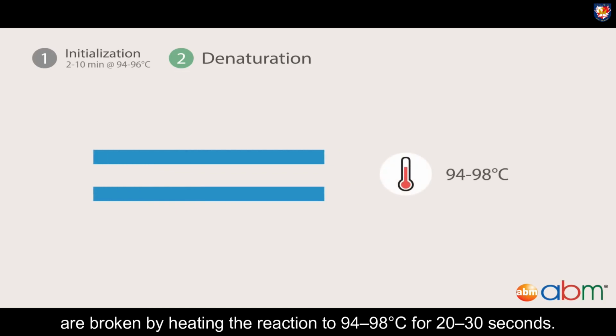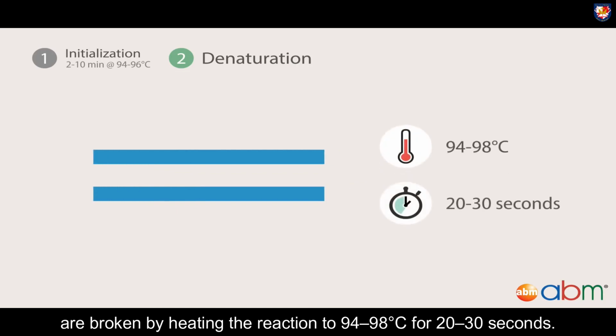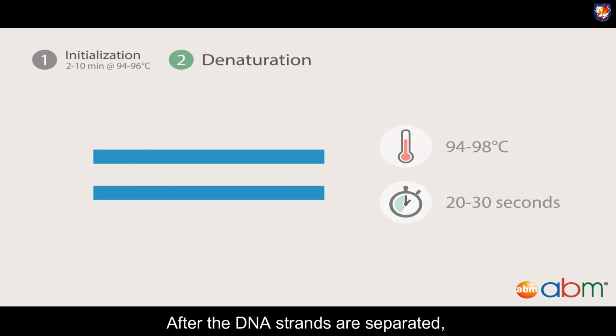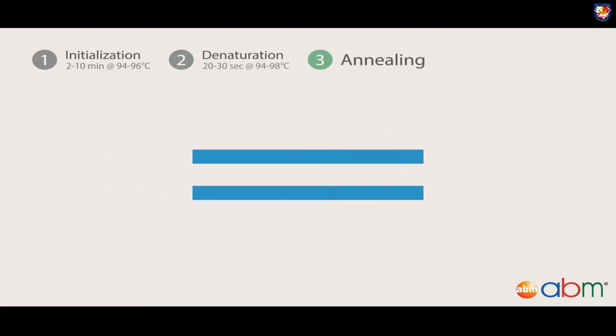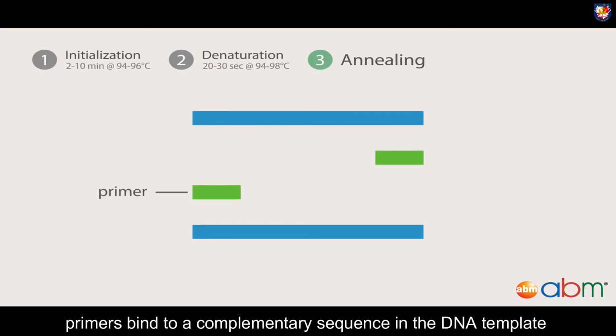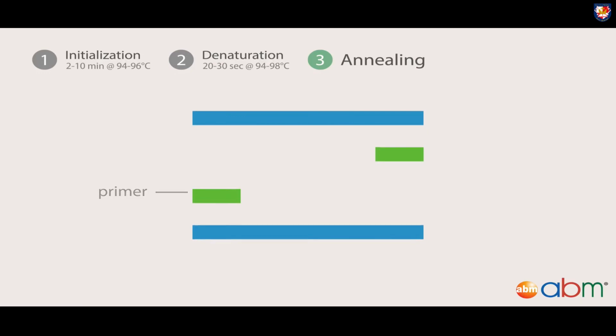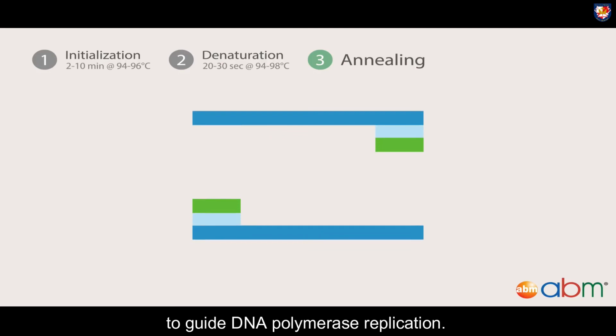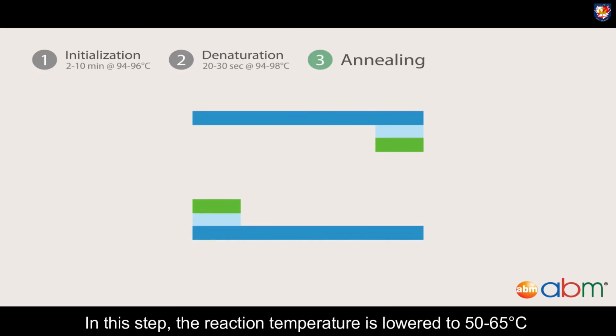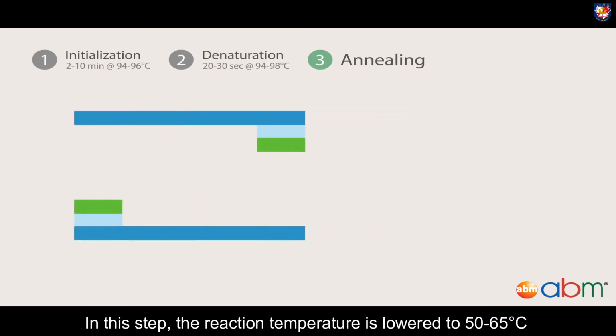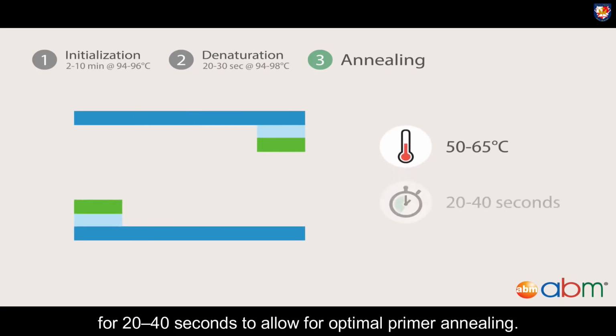In the denaturation step, hydrogen bonds between the double strand of DNA are broken by heating the reaction to 94 to 98 degrees Celsius for 20 to 30 seconds. After the DNA strands are separated, primers bind to a complementary sequence in the DNA template to guide DNA polymerase replication. In this step, the reaction's temperature is lowered to 50 to 65 degrees Celsius for 20 to 40 seconds to allow for optimal primer annealing.